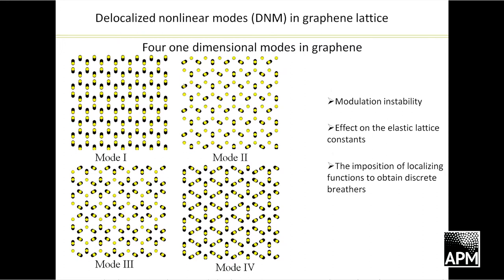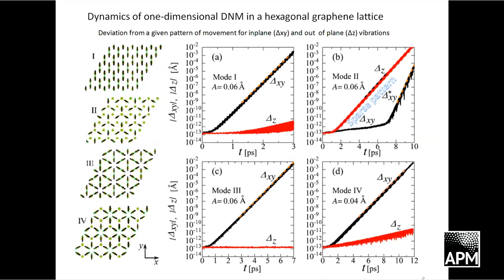In graphene we have only four one-dimensional modes. One-dimensional means they can be defined by a single equation of motion. For the hexagonal lattice, these four and only these four vibrational patterns were proven by Georgy Chechin and Denis Ryabov using theoretical group methods. It is important to study these modes because they can cause modulation instability and affect the elastic constants of the crystal. We can also use a localization function to obtain discrete breathers from delocalized modes.